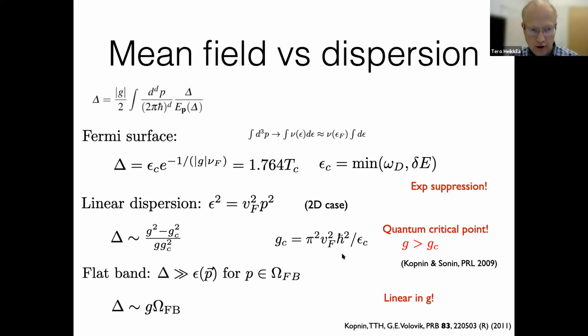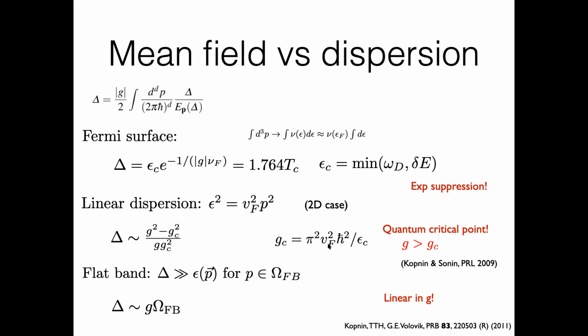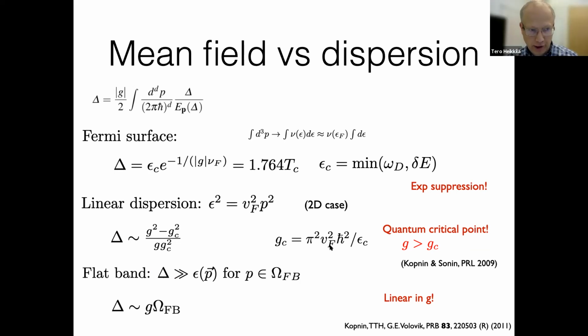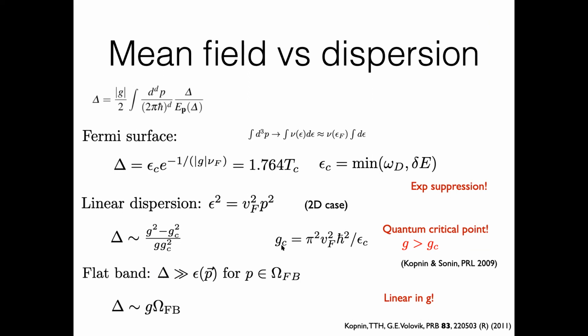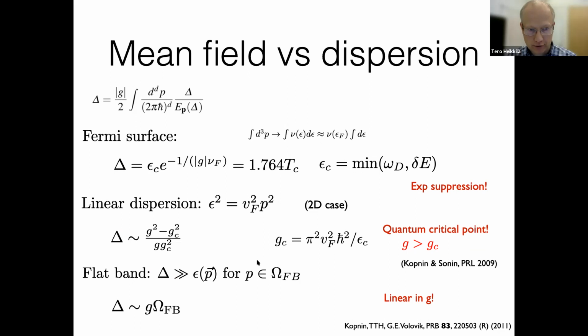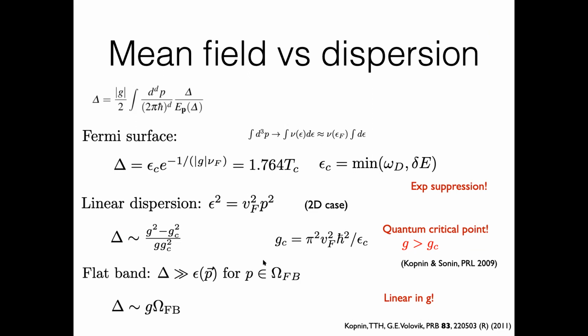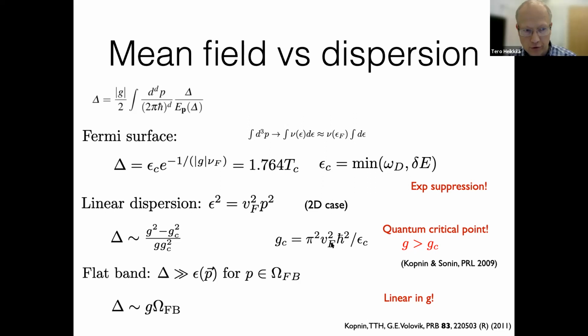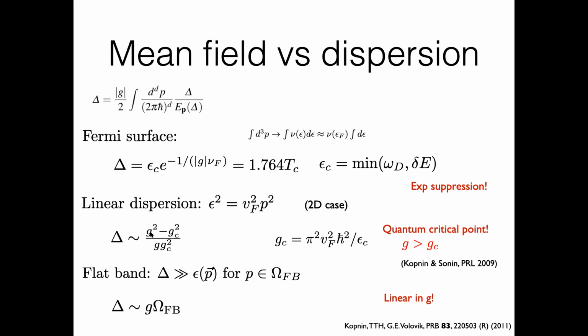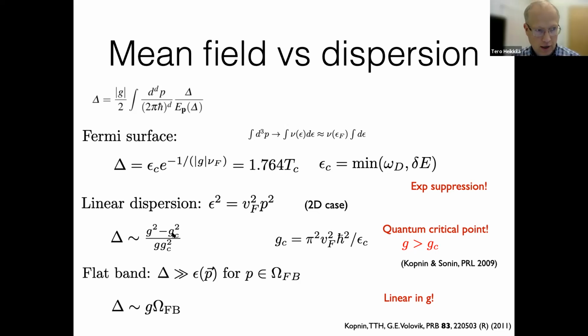Excellent question. Actually, I will show a picture about this, but a hint to this picture is that the critical coupling strength depends on the speed. So if you reduce the speed, the g_c becomes actually smaller. And this way you actually can interpolate between the two cases. So if you reduce the coupling to 0, would you get a linear dispersion? Because it seems that if you reduce the velocity to 0, indeed you get linear from here. So if you take g_c to 0, then delta goes like G. Right. Okay. Yeah, there are other things, of course, but this is just a mean-field solution of these equations. But that was a good question.